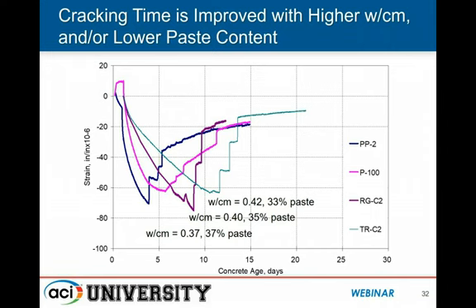And there are plenty of situations when strength is most important. Obviously, for construction sequencing, form stripping, moving to the next level in a high-rise structure, your compressive strength is dominating the early behavior, and that's really what you want. But in the cases I'm discussing today, I'm veering towards the patching and the paving materials and bridge decks. It's not compressive strength that drives us. It should be the cracking behavior, and we need to be able to accommodate that to a greater extent. So this is where this type of mixture design approach, where we can start to promote cracking-resistant materials like the very last trend line here in green, the one farthest to the right. Now we've gotten towards a good compromise. It's a 0.42 water cement ratio, 33% paste.